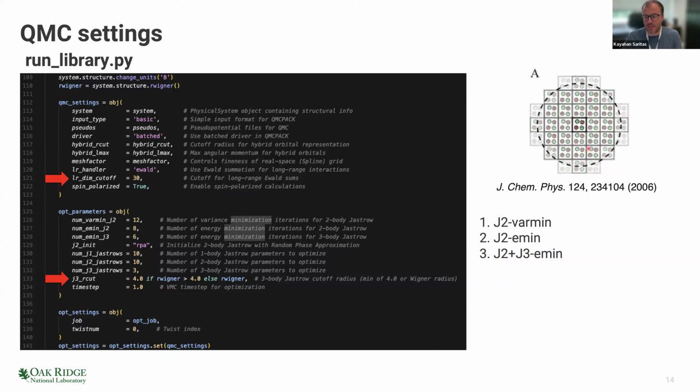As you can see, this is shown in real space, but this cutoff corresponds to reciprocal space. I think the default parameter should be around 15 to 20 if you are working with three-dimensional systems. But in 2D systems this cutoff might be larger, because you're looking at convergence around a two-dimensional surface of a material, which may have less screening than a three-dimensional material.